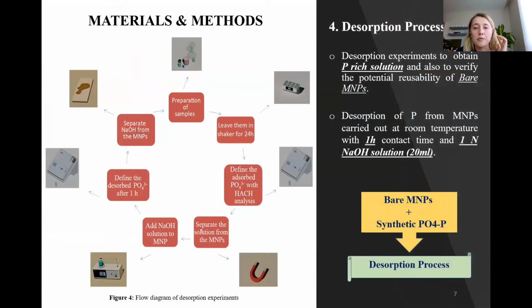And now we have the desorption processes. Well, to determine the reusability of the bare magnetic nanoparticles and the availability of phosphate recovery, a desorption experiment was carried out. The flow diagram of the desorption experiment is given in figure 4. The steps are very similar to the adsorption processes. However, the desorption of phosphorus from bare magnetite nanoparticles was carried out at room temperature with 1 hour contact time and 1 normality of sodium hydroxide solution.